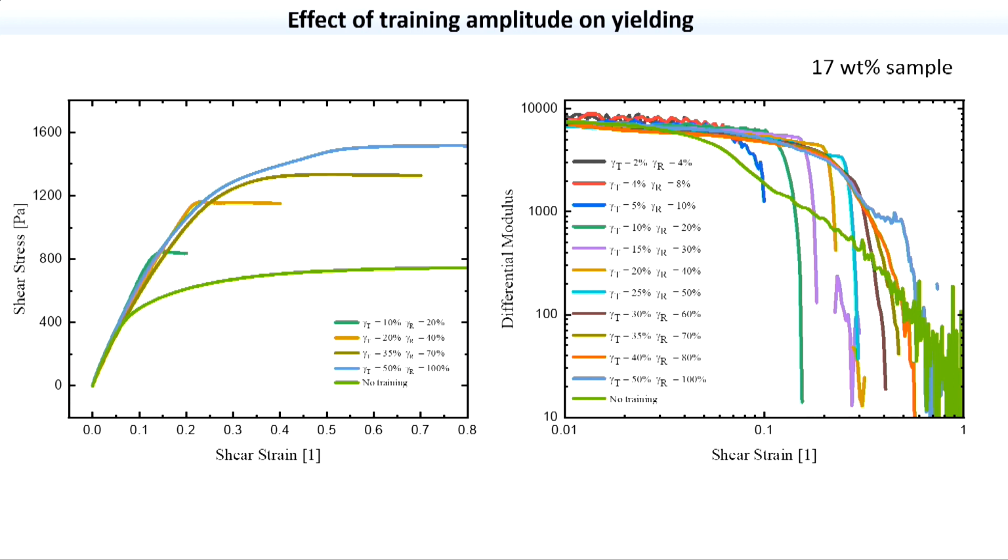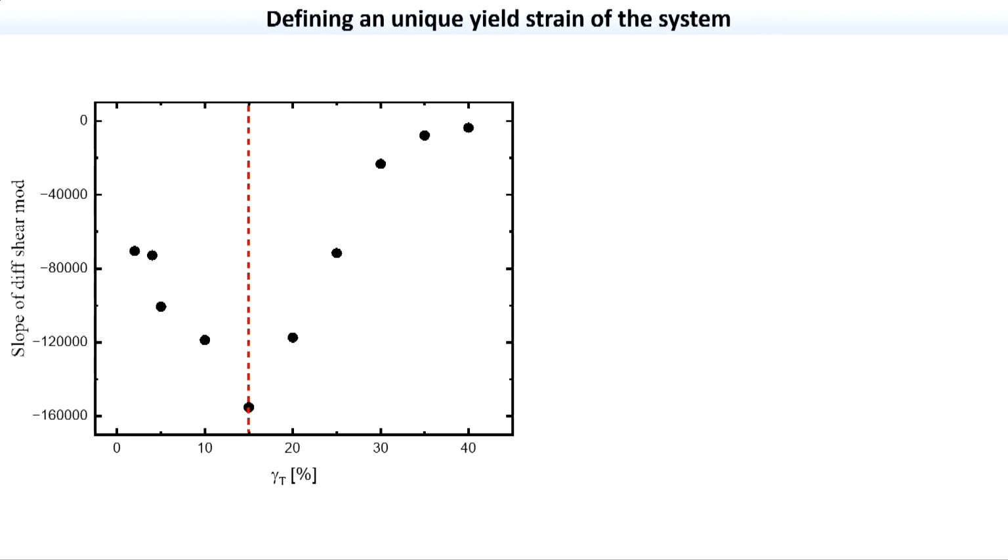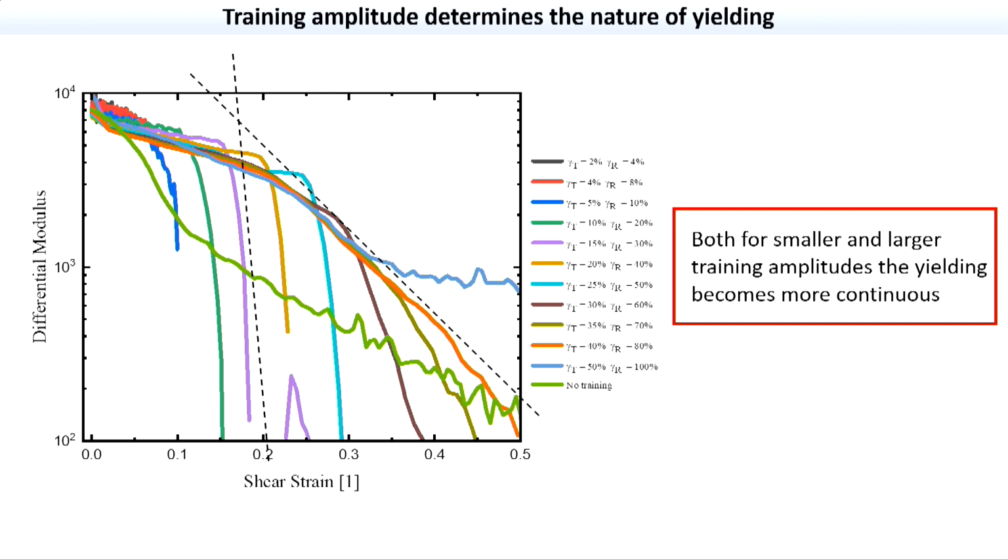So now, if you look at the rapidity of this fall, what does it mean? If I have a very stable system, and as it yields the modulus falls very rapidly, it means it's a very drastic yielding. So this double derivative of this curve, which will give you the single derivative of differential shear modulus, will indicate how drastic your yielding is, right? Now if we compute these slopes, in this region at least